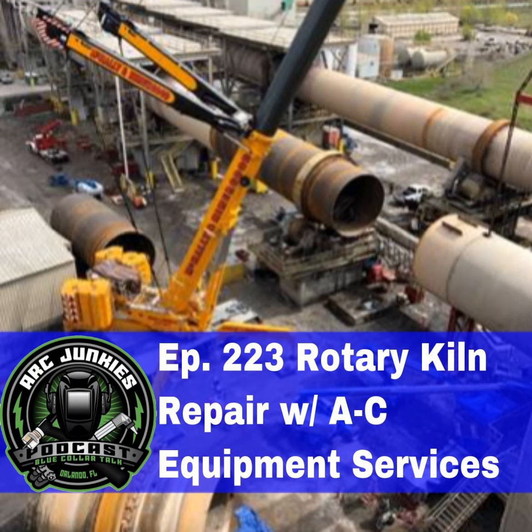Damn. So when you guys do your flux core root pass, I mean, we're cutting that out anyway. It's a sacrificial root pass. Yeah. You said you're gouging out from the inside, but when you run that flux core pass, are you using gas shielded flux core, or self shielded flux core? No, we typically run a 70 series dual shield flux core. Okay. 1/16 diameter, run everything with pretty much Miller wire feeders.